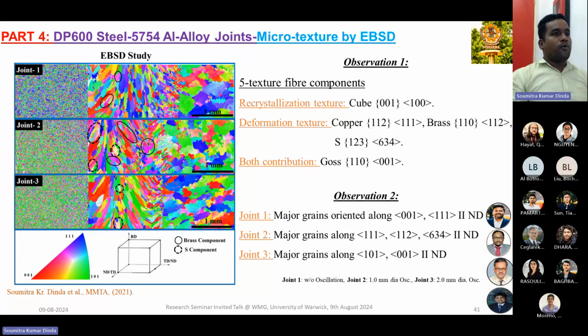But from our result, for joint 2, we see that the major components are oriented in the 111, 112, and 634 directions. That is the deformation texture. That means before going to fracture, we will get the maximum mechanical property in case of joint 2.